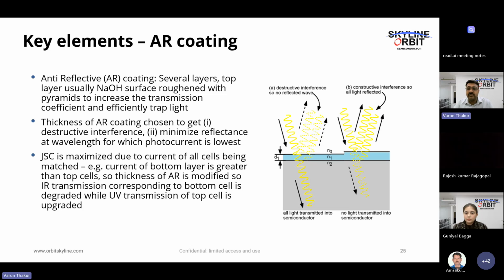So here also we can do a lot of engineering. For example, the thickness is chosen such that only destructive interference takes place, and so we destroy any kind of reflection, and we minimize the reflectance at the wavelength for which photocurrent is lowest, right? So these are all things that we have to keep in mind when designing the ARC, which is the anti-reflective coating, right? So that is why the current density is maximized. So the current of all cells will be matched, and the current of the bottom layer is greater than the top cells. Okay. So I'm not going to read through this.